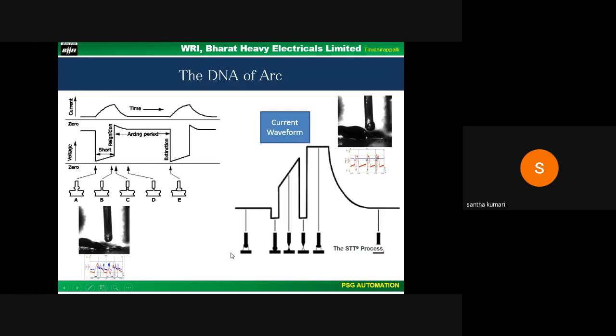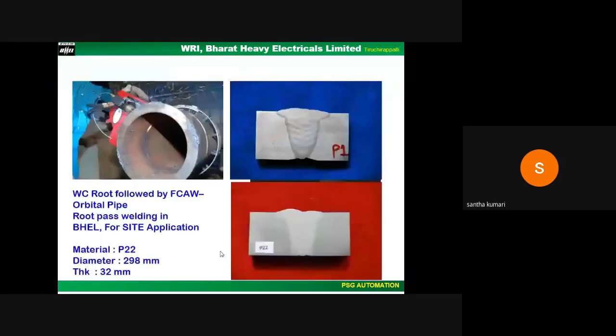Here a power source had been studied for root pass application in pipe welding, and the same was used for root pass welding of pipe and further processed with the flux core arc welding process to achieve a very good weld of 32 thick pipe for site applications. We used one of the waveform controlled power sources.